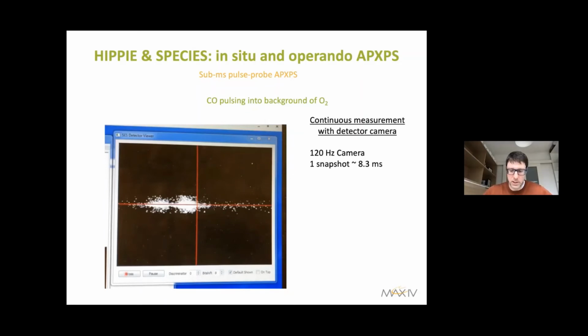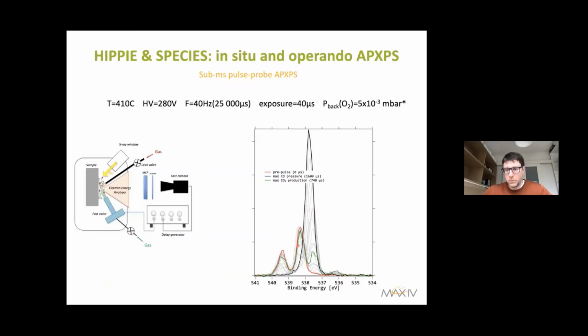Let me run it again. Yes, now it's running. The two peaks on the left are the gas phase oxygen doublet. The peak which is appearing here is CO. So you can really see the background of oxygen and the pulsed CO inside it. We can measure the individual spectra of the gas phase at different time delays. Some of them are shown here.